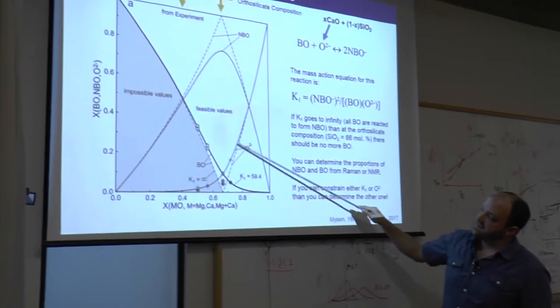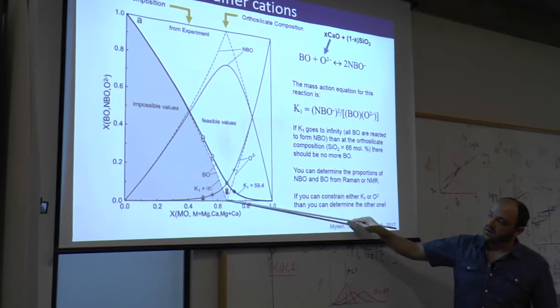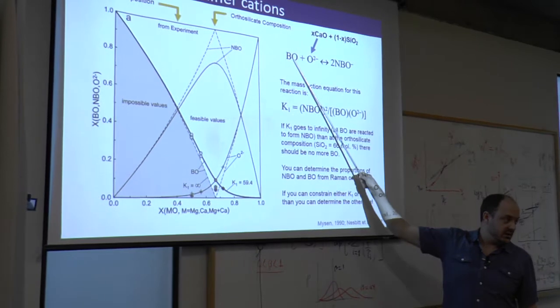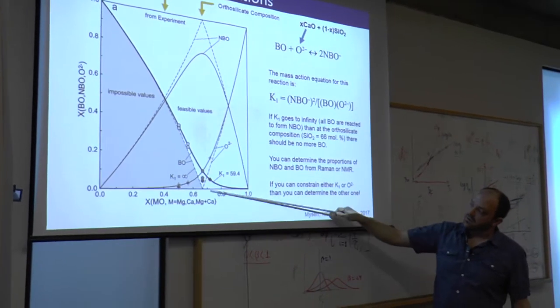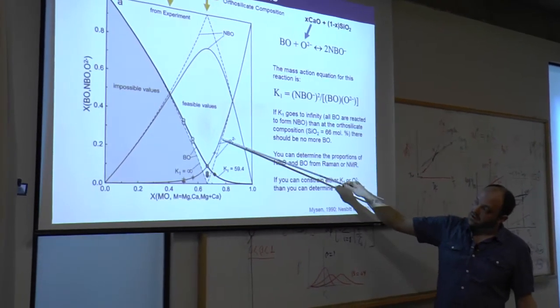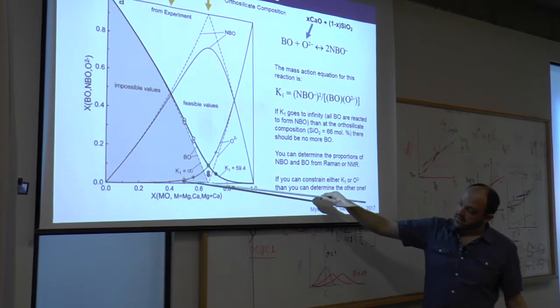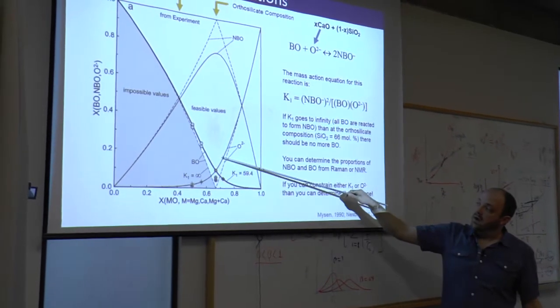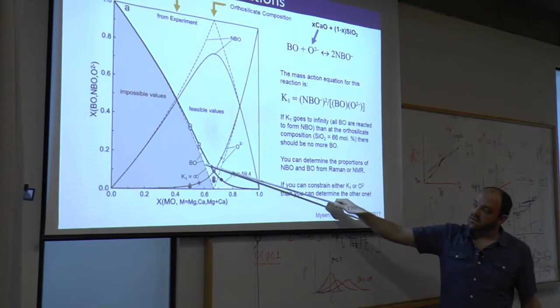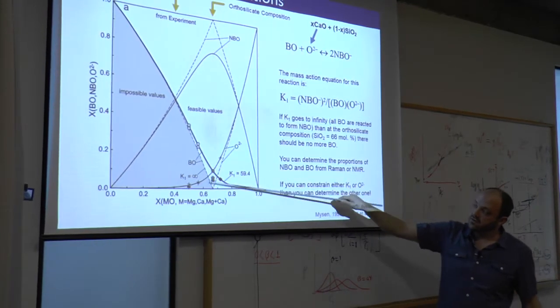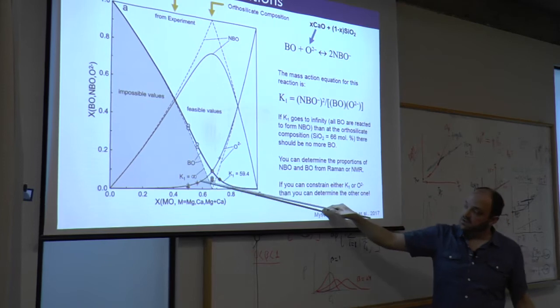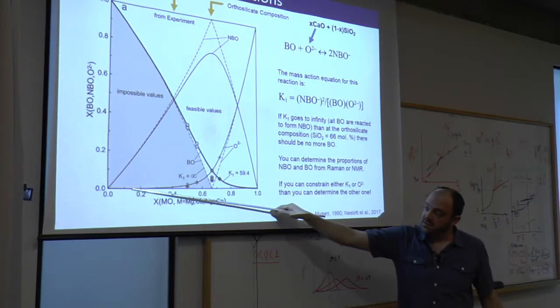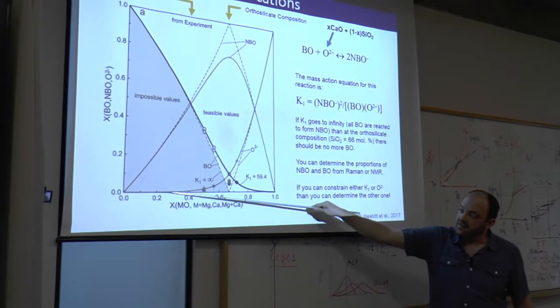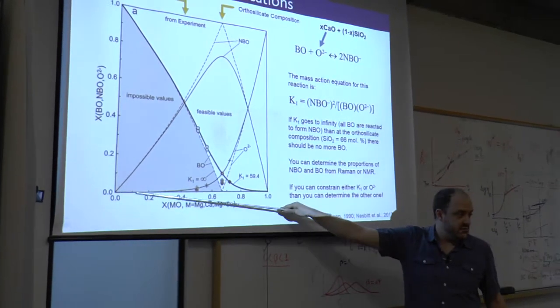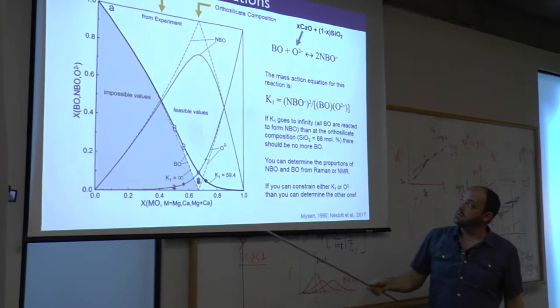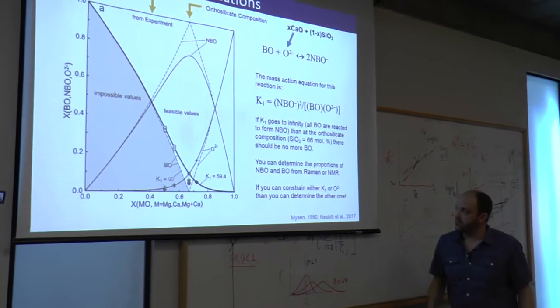The first is that instead of only producing free oxygen after all of the bridging oxygen is converted to non-bridging oxygen, we produce this non-network oxygen at much lower compositions. And in a lot of papers, something to be aware of is that they've assumed that this reaction goes to infinity and that there's no free oxygen in these intermediate compositions, but there should still be a tiny fraction even as soon as you add a modifier to your pure silica network.